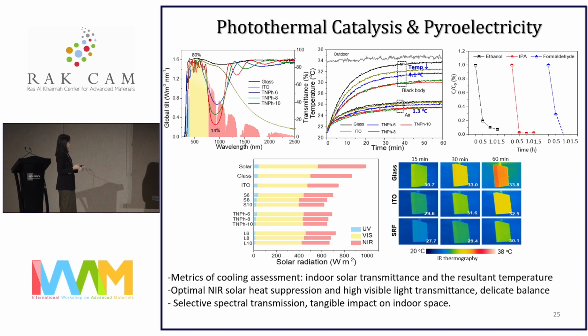With selective UV, visible and near-infrared spectral transmission tuning and optimization, we have a direct and tangible impact on the indoor space, with a temperature reduction of about 4.1 degrees Celsius black body and 1.3 degrees Celsius air. And here, IR thermography images show that the nanophotonic film has very consistent cooling results. TiO2 being one of the key compositions of the film means that it can enable photocatalytic degradation of organic air pollutants to be realized.